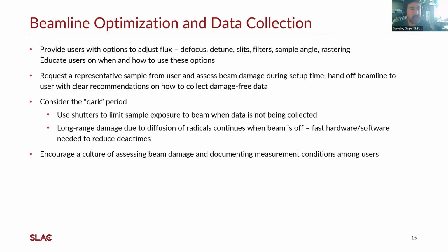Yeah, hi. Well, we did discuss this as well in our soft tender X-ray spectroscopy group, and we are aware that we have seen in beamlines that work with tender X-rays very often some radiation damage that is due to the fact that the interaction is more likely, so that there are more atoms involved, and as well the fact that you use the electron, possibly the total electron yield, you might be extracting electrons that can cause it as well.